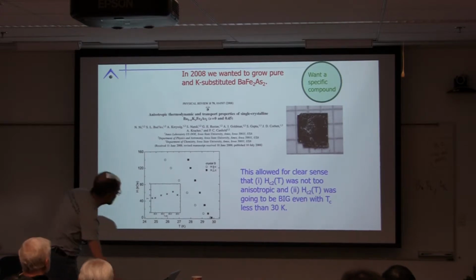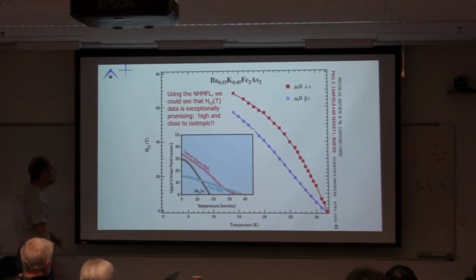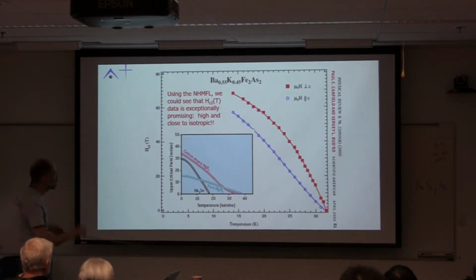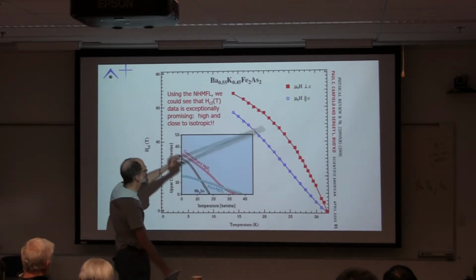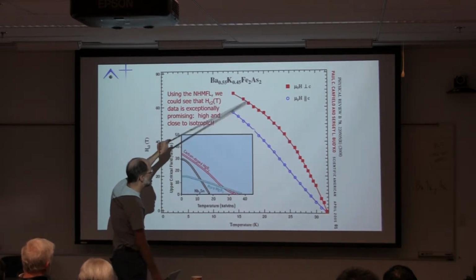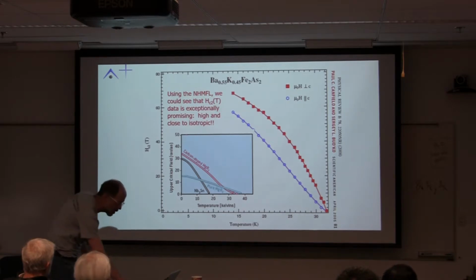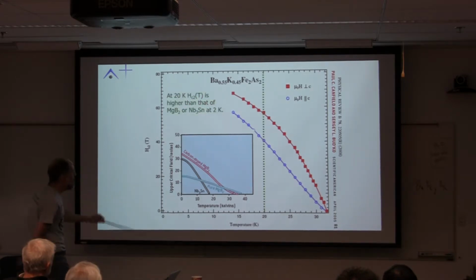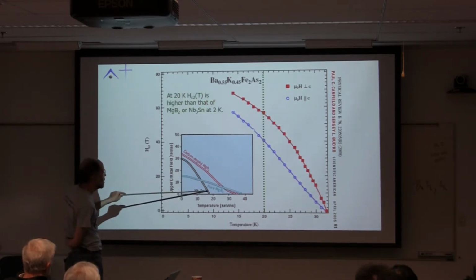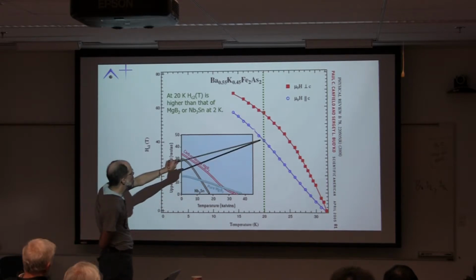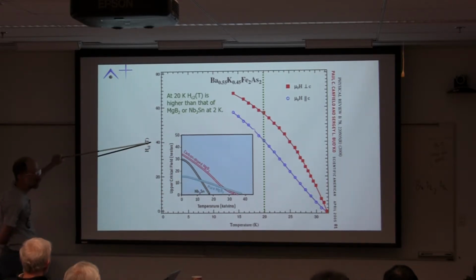Now, this required going to the National High Magnetic Field Laboratory, where we could go to higher fields. We can see that Hc2 is indeed really large. The anisotropy is getting smaller as we go to higher fields. And if you remember, 20 Kelvin was sort of exciting for MgB2. Well, at 20 Kelvin here, the lower Hc2 is in excess of 40 Tesla.